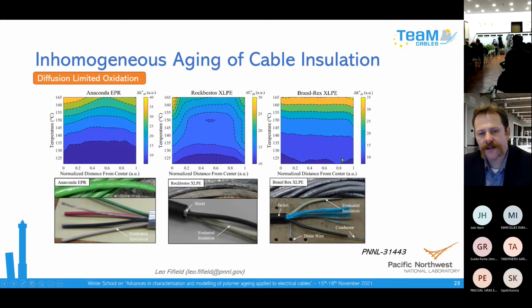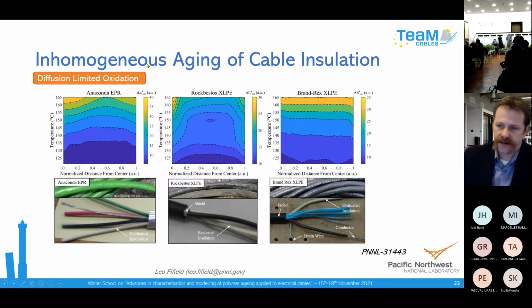So I'll talk about another recent effort, which was to look at this knowledge gap related to diffusion-limited oxidation. As I mentioned, this is when you have rapid aging at the edge of a sample, and it actually prevents aging from the interior of the sample, which can lead to a misunderstanding when you try to extrapolate accelerated aging to mild service conditions. In this case, we looked at a few different materials: an Anaconda EPR, Rockbestos XLPE, and a